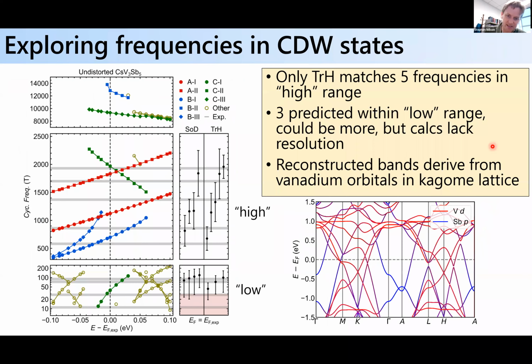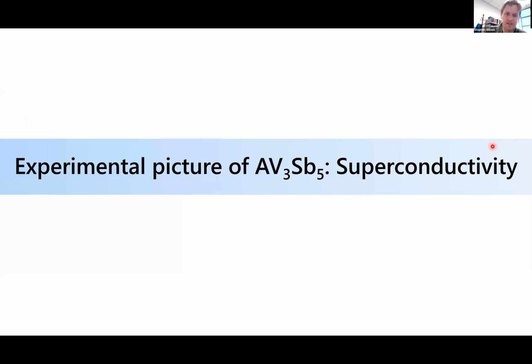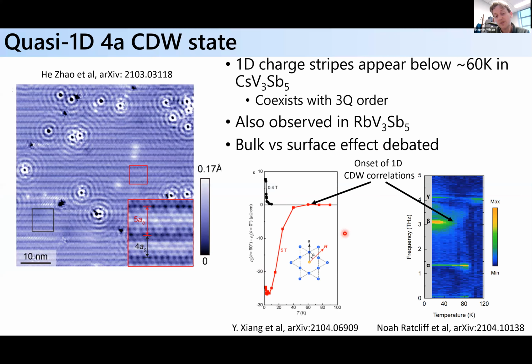Okay, yeah. So the in-plane anisotropy, the proposed evidence is from transport along the C-axis, but basically all they're doing is rotating the magnetic field in the AB plane. So I think they're claiming that there's some in-plane anisotropy that they're picking up by doing this. And we've done similar measurements, and we do see some anisotropy on our crystals as well that turns on at low temperatures. Some sort of C3 symmetry breaking.